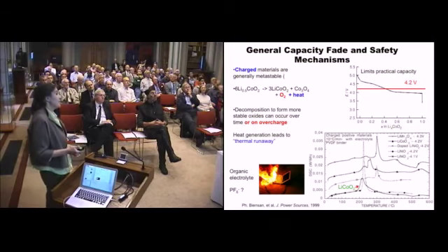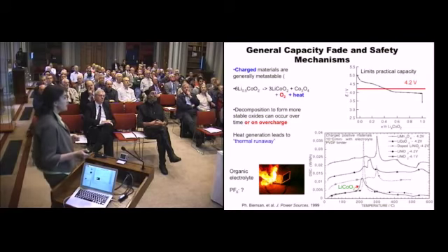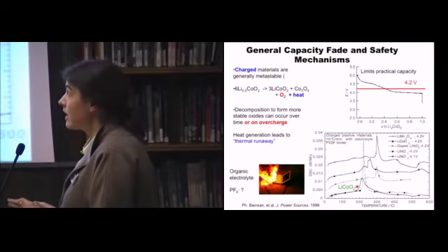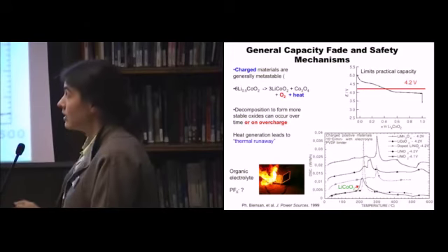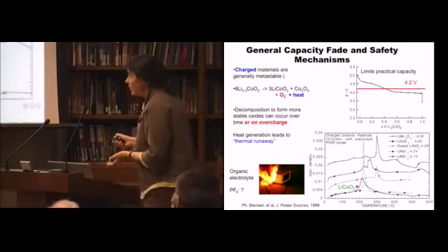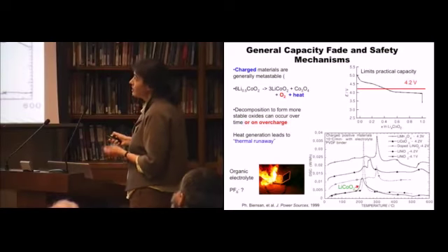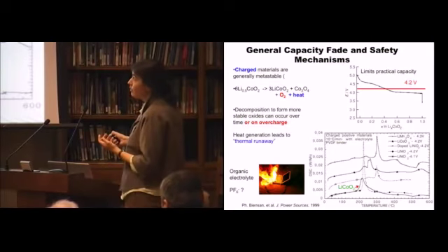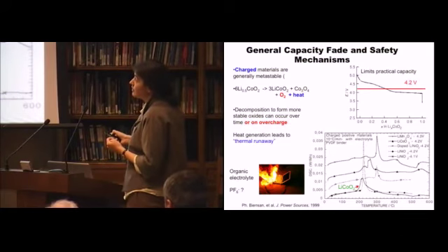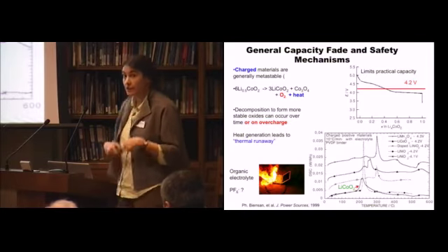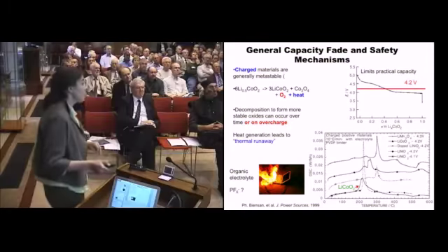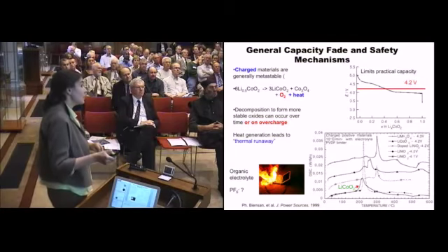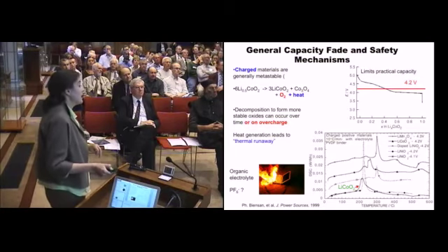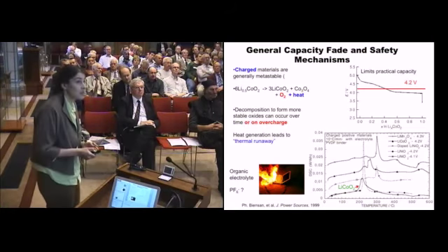So the thing about a material, you make it in the lab, and then you pull lithium out of it. And when the lithium's been pulled out, it's generally metastable, which means it's not in its most stable state, and therefore over time it can decompose. So lithium cobalt oxide, if there's heat or even just time, will decompose to give the original lithium cobalt oxide and another oxide and oxygen and heat. And this heat then can cause more decomposition, and you can get this thing called thermal runaway. And it's this thermal runaway that produces the oxygen that then reacts with the organic electrolyte to cause these fires. And so that's one of the most serious safety issues.